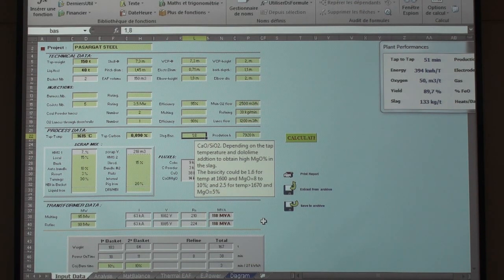You have this small comment. The slag basicity can be reduced, for carbon steel, I mean construction steel, down to 1.6 if you are sure to tap below 1,600 and to have saturation of magnesium from 8 to 10% of the slag. And if you want to increase the tapping temperature for special application, for example 1670, then you have to increase to 2.5, and MgO minimum 5%. The saturation in this case is in the range of 11.